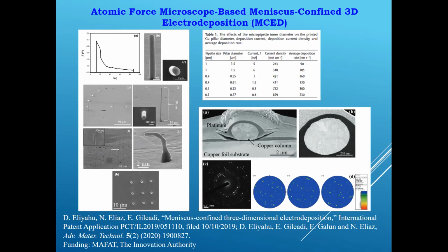These are important advantages of electrochemical 3D printing over conventional metal additive manufacturing technologies, such as powder bed fusion and directed energy deposition. The quality of the pillar is also higher than in most previous fabrications dealing with electrochemical microprinting with other control schemes. Figure D and E show scanning electron microscope images of copper pillars printed from a micropipette with an orifice diameter of 400 nanometers. The actual diameter of the printed pillar is always larger, around 500 nanometers in this case. Note that the pillars do not bend and that they have high aspect ratios.